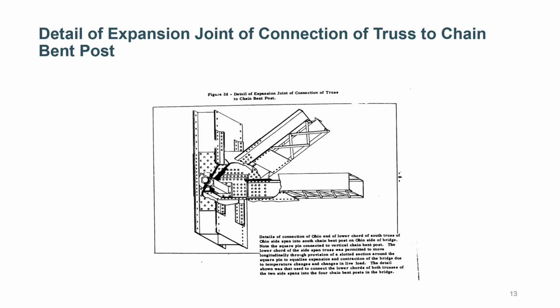The initiating failure: a cleavage or brittle fracture in eye bar number 330, which was the north bar, north chain, Ohio side span, at joint C13N. A small semicircular crack, approximately 0.1 inches deep in the eye's inner surface, split the lower half brittly, then the upper half ductilely. This let the companion eye bar number 329 slip off the pin, severing the chain.